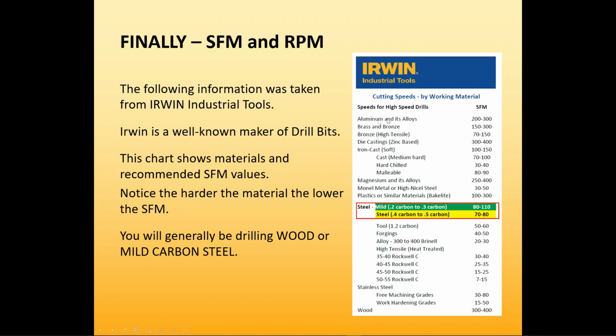But up at the top we've got aluminum, bronze, brass, cast iron, magnesium, plastics, and then we've got steel. The hardest steel we have here is a high carbon steel that's been heat treated to a Rockwell C hardness of 50 to 55. And we can see right here that if we have a piece of steel that hard, our surface feet per minute can only be somewhere around 10. Okay, 7 to 15.